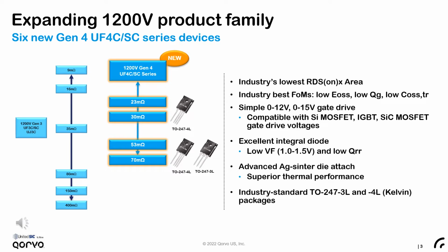The new parts offer the industry's lowest RDS(on) times die area, along with all the additional benefits that the lower conduction loss per chip size affords. They have the industry's best figures of merit of RDS(on) times EOSS, a lower gate charge, and lower output capacitance. As with all the United Silicon Carbide FETs, they feature a simple 0 to 12 volt or 0 to 15 volt gate drive, and they're compatible with silicon MOSFET, silicon IGBT, or even silicon carbide MOSFET gate drive voltages. They feature an excellent integral diode with a lower VF, typically between 1 and 1.5 volts, and have a low reverse recovery charge. These products also feature an advanced silver sinter die attach, which gives them superior thermal performance.